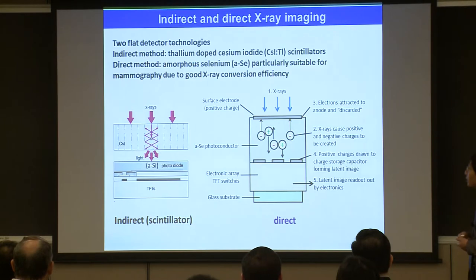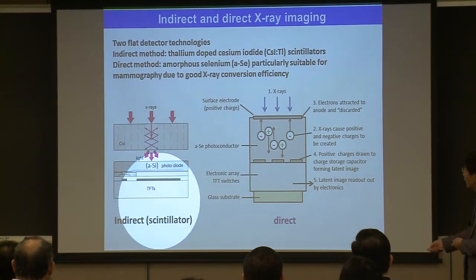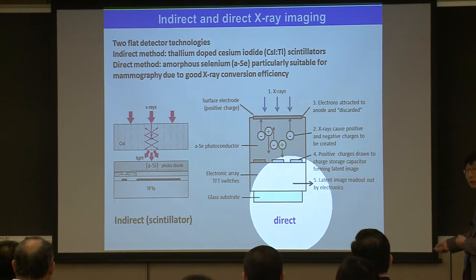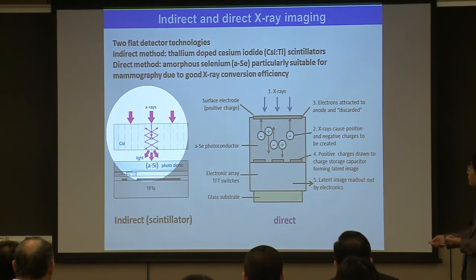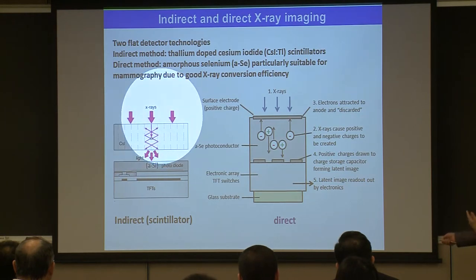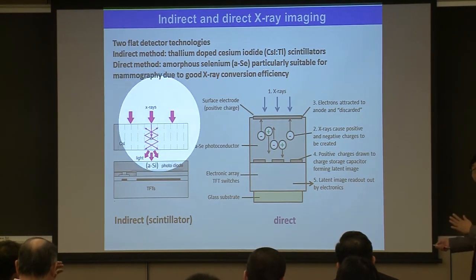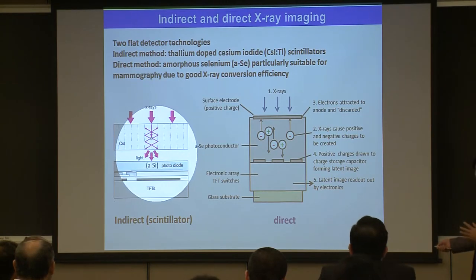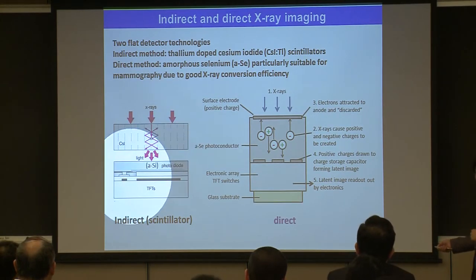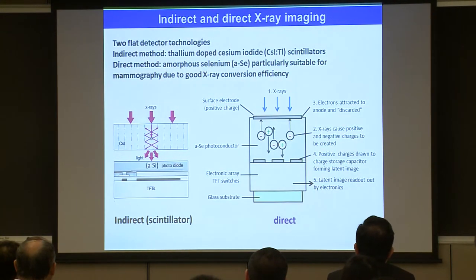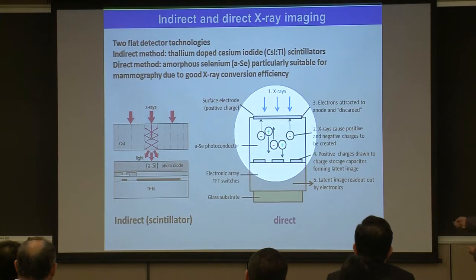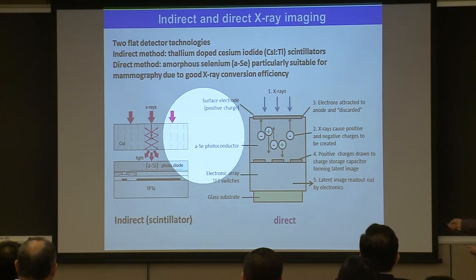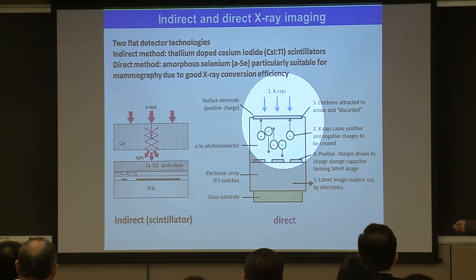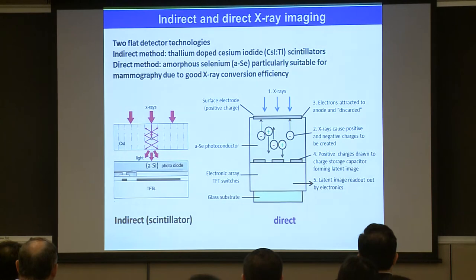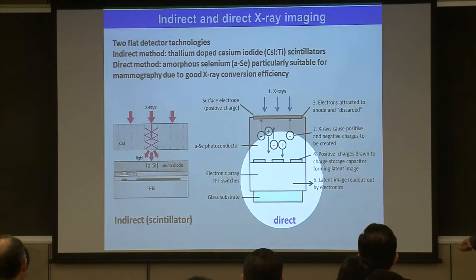So there are two methods. The indirect method is called the scintillator method. We also have a direct method. In the scintillator method, for instance, cesium iodide is a well-known material, absorbing X-ray photons and emitting visible light, which is detected in an amorphous silicon photodiode, and then converted to an electrical signal. In the direct method, you deposit the photo detector, such as amorphous selenium, a well-known material, directly on the TFT back plane. So we studied the direct method.